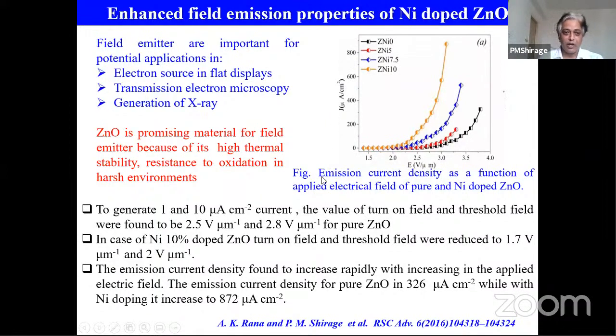Basically charges. There are two definitions: turn on field and threshold field. The field required to generate 1 microampere per centimeter square of current is called the turn on field, and when it reaches 10 microampere per centimeter square of current, that's called the threshold field. In the case of zinc oxide, the turn on field and threshold field are 2.5 volt per micrometer and 2.8 volt per micrometer. In the case of 10% nickel doped zinc oxide, the turn on field and threshold field become lower. It means that we need very low energy to reach them. This is 1.7 and 2 volt per micrometer. So nickel doped zinc oxide is very good for field emitters.